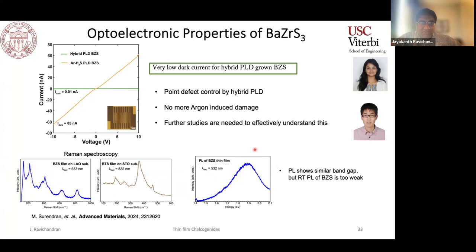PL seems to be not so sensitive a probe here, primarily because of something very intrinsic to BaZrS3. But nevertheless, I think our optoelectronic measurements seem to have a much better handle on probing its quality than even PL or other pure light-based optoelectronic studies.